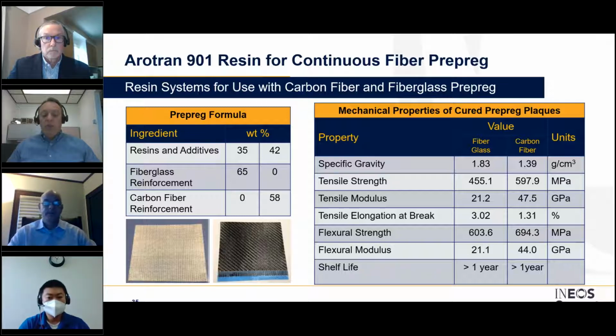I will note here that we recently molded some prepreg that we've stored in our lab at ambient conditions for more than 5 years and noted virtually no difference in the tack and flexibility of the prepreg prior to molding, nor any significant difference in the molded part. The typical prepreg manufacturing techniques, like vacuum consolidation, were utilized, followed by a short cure cycle in the compression mold.